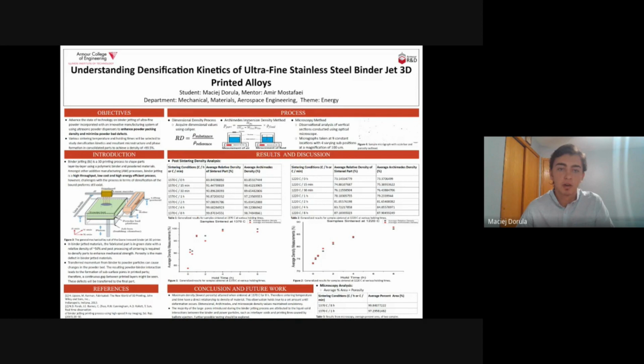The majority of the large pores introduced during the binder jetting process are attributed to the liquid-solid interactions between the binder and powder particles, such as the interlayer voids and printing lines caused by ballistic ejection. Further possible testing should be explored.